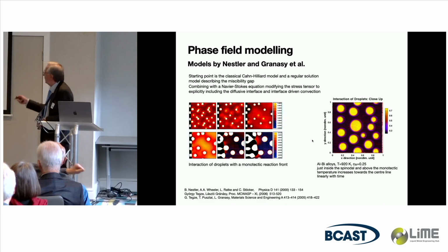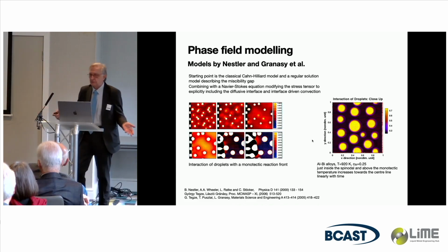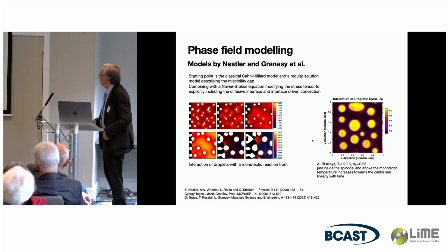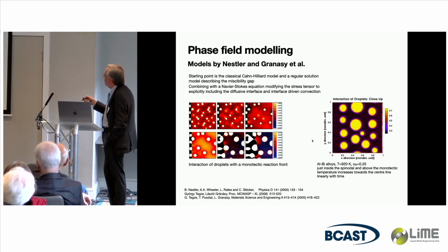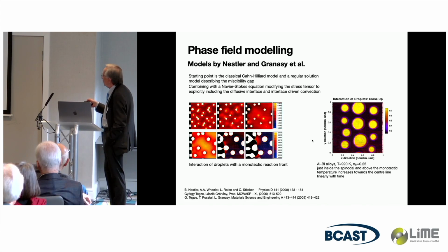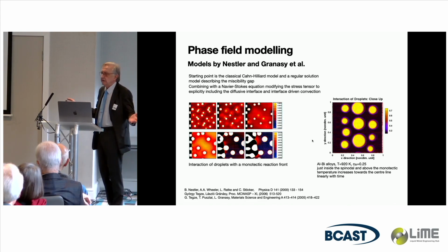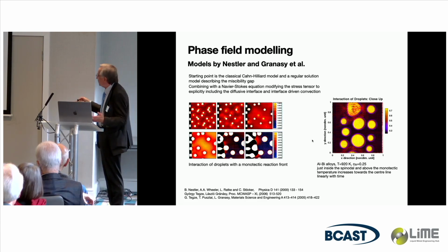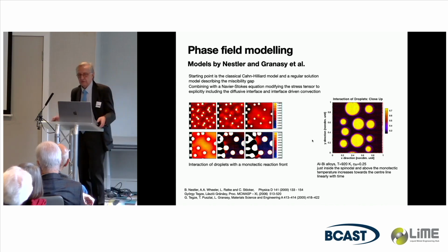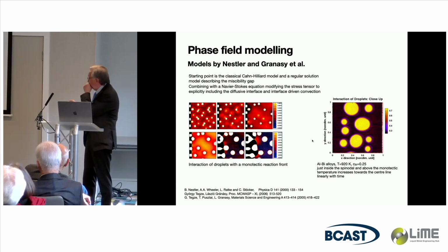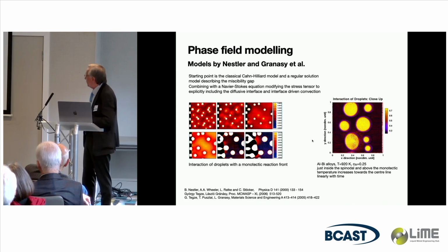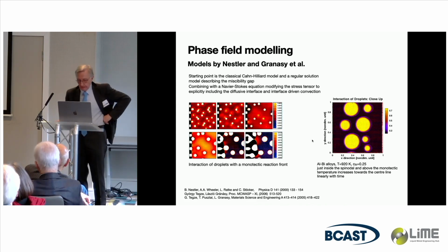Because in the spinodal, concentration fluctuations do everything by themselves. They amplify by themselves. And what you nicely could see is that the droplets, in as much as they come closer, they interact. This is the way the interaction of hydrodynamics in reality works. This is wonderful. So it's really doing at the end a big blob.